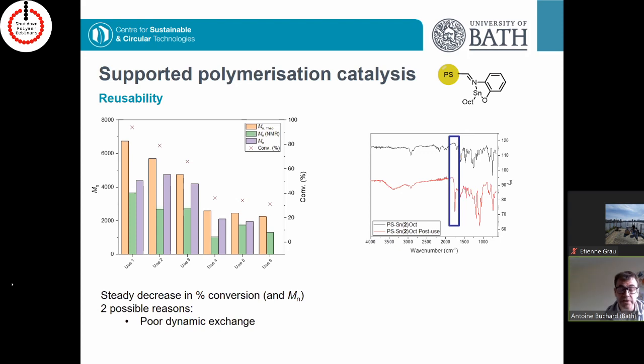with those heterogeneous catalysts is the possibility in the end to reuse them, because what we produce are essentially beads that you can pick up with tweezers or you can filter. So we had a look at this as well. And you can see here that reusing several times this type of catalyst, we could see a clear, steady decrease in percentage conversion of lactide, as well as molecular weight, for we think 2 possible reasons.